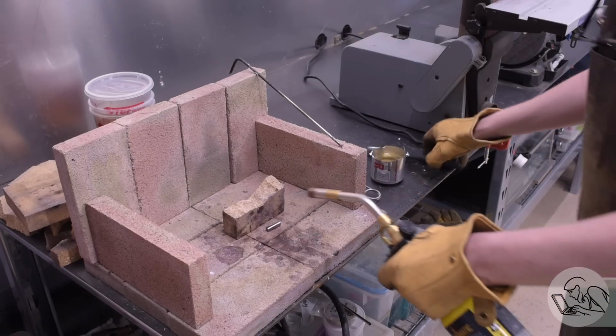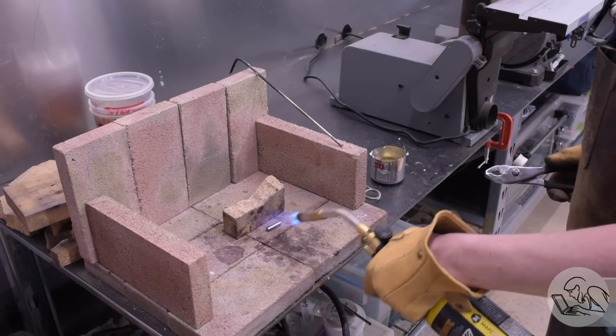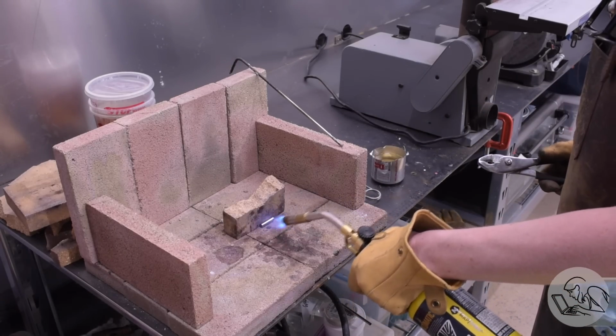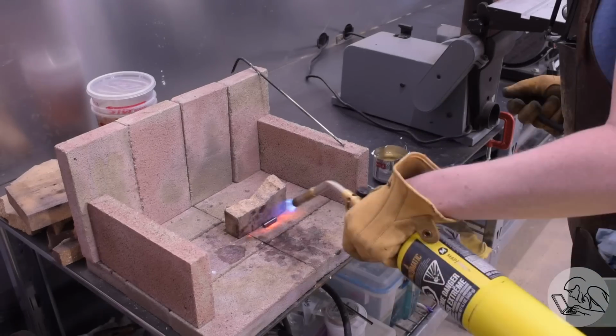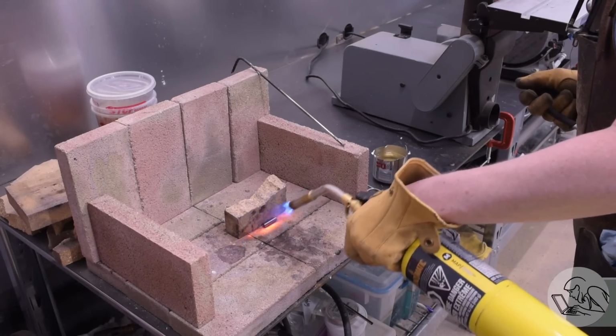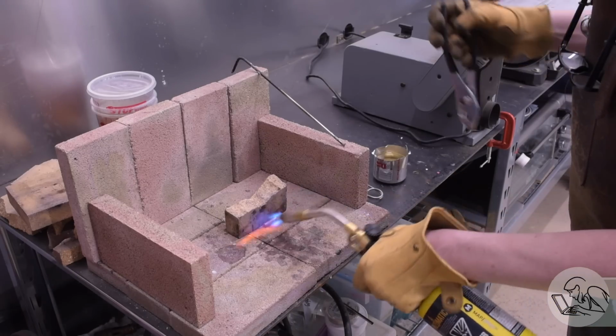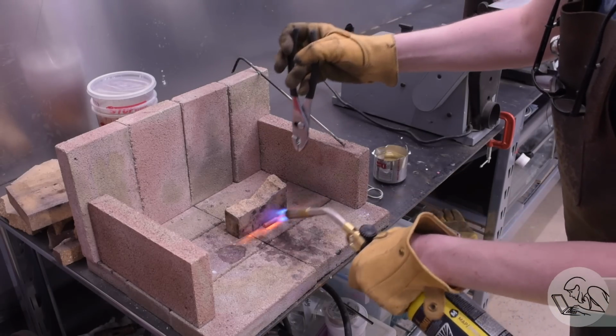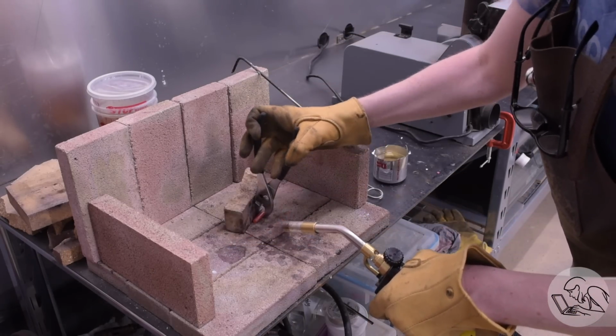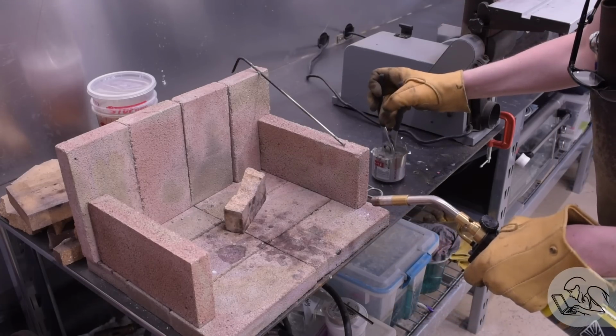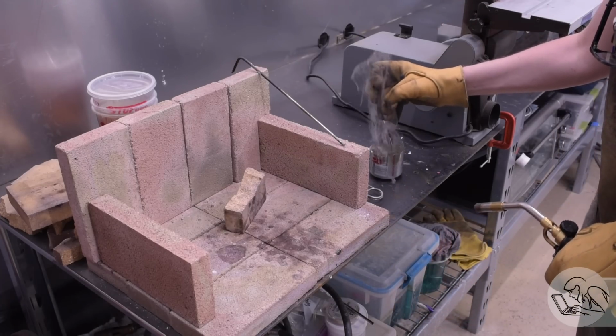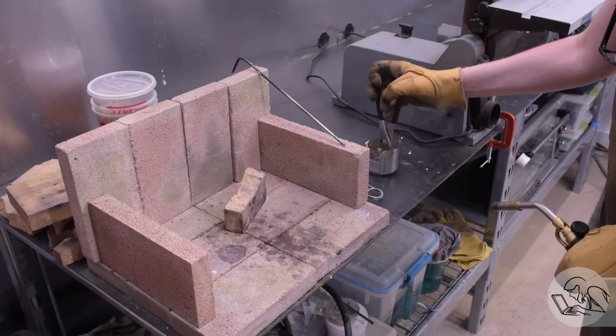The reason I used tool steel for these crank pins is because they are going to be hardened. These crank pins are essentially the inner race of a bearing, so they are going to get a lot of wear and tear, and it's thus recommended that they be hardened and tempered. So start with the hardening. I heat that to cherry red, and then dunk that in oil, swirl it around in the quenching oil. I'm using canola oil for this because it makes the shop smell like French fries.